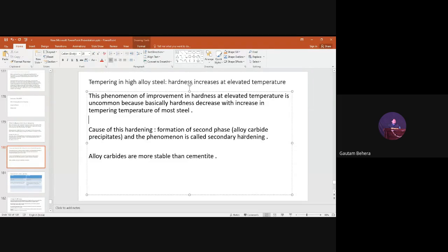Secondary hardening. Hardening due to second phase particles. Precipitates are the second phase particles. Primary phase is your matrix. It may be austenite, it may be ferrite, it may be bainite, anything, right? But the second phase is nothing but the particles. These are the carbides. The same thing happens in my steel, because I have vanadium, titanium, niobium, tungsten, chromium. They form stable carbides at high temperature. So when you do tempering at an elevated temperature, these carbides start forming in the steel. These are the second phase precipitates, right? If you remember, precipitation strengthening will happen because the dislocation will move, and this dislocation will get pinned by these precipitates.